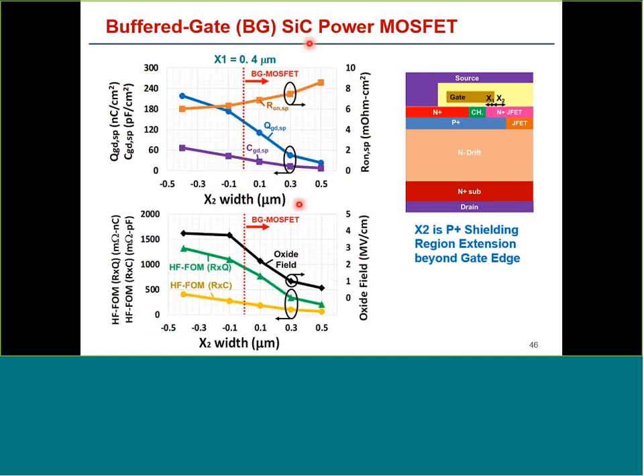I'm going to focus here on the BG MOSFET, and you can see here that as X2 is made larger, in other words, the P+ region is going further and further out, we're getting a big reduction in CGD and QGD. The thing again you have to watch out with this design is that if you make this P+ wider and wider, then you get more and more resistance from this portion, and the RDS(on) starts going up. So if you include the impact of the change in RDS(on) and the values for CGD, QGD, you get these figures of merit, and you can see a very substantial reduction of the RQ and RC figure of merit with this structure.